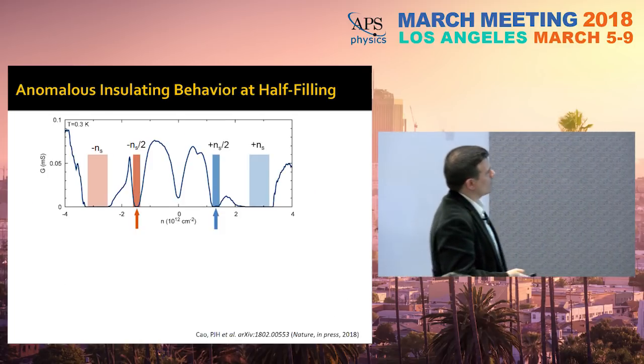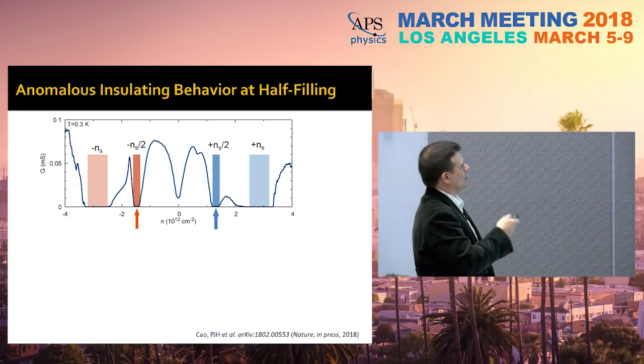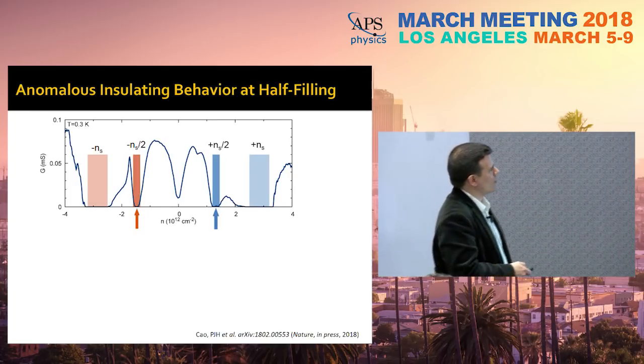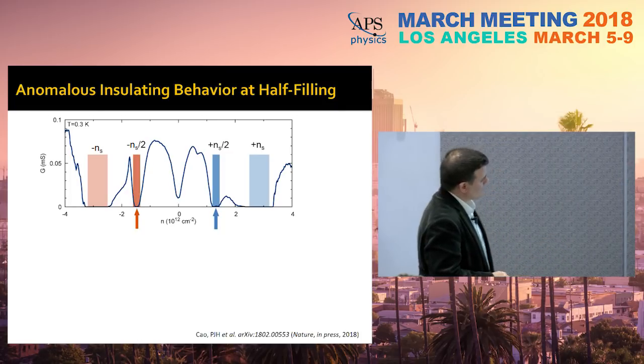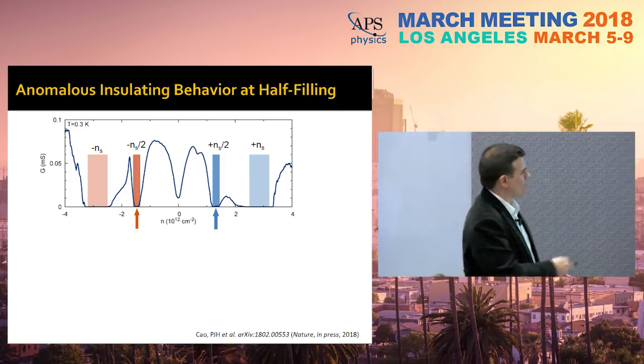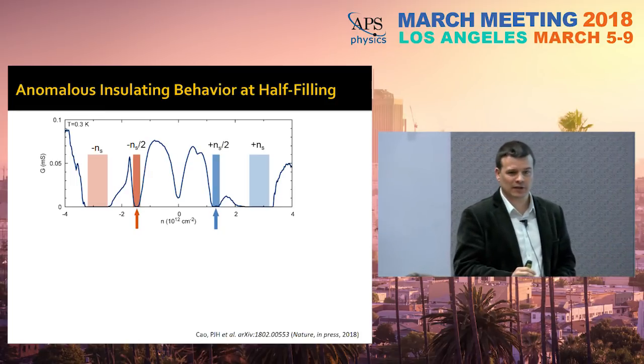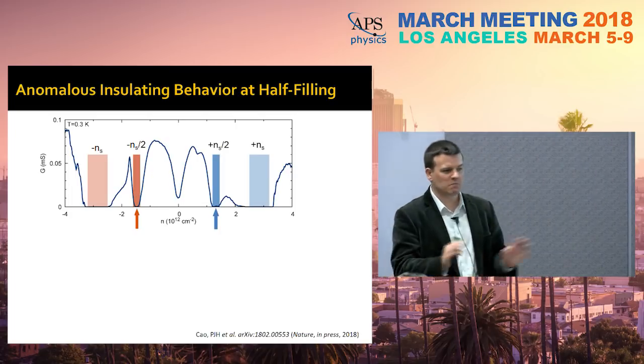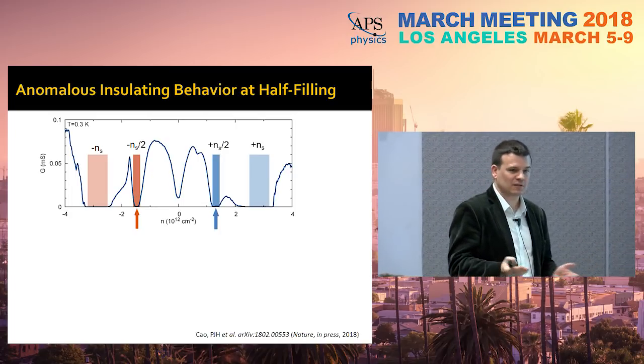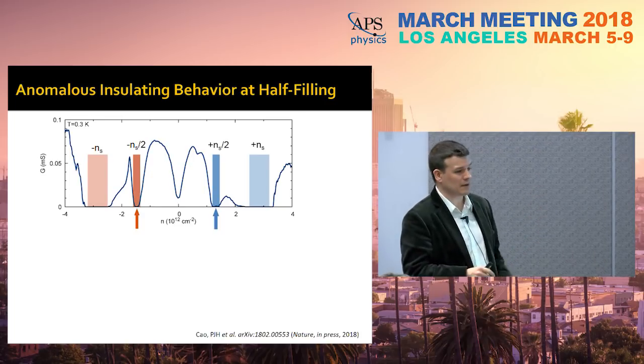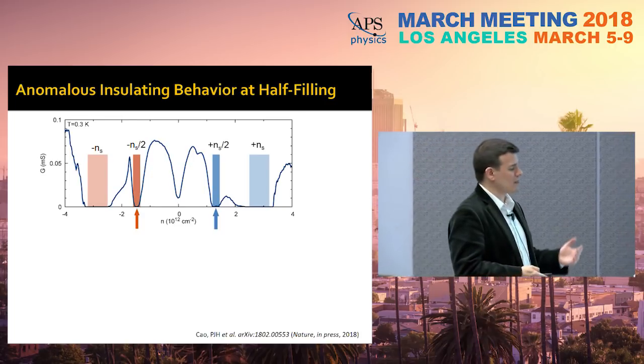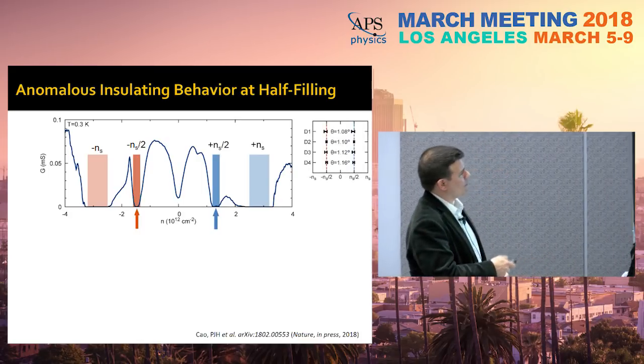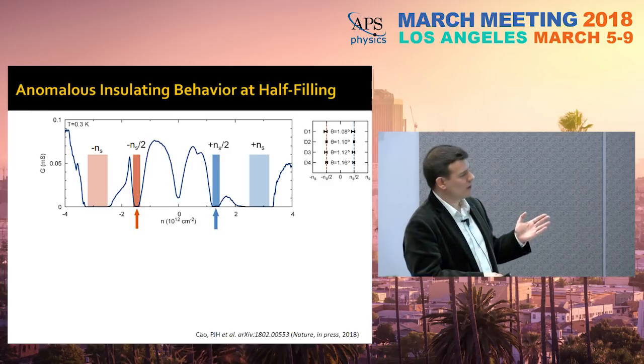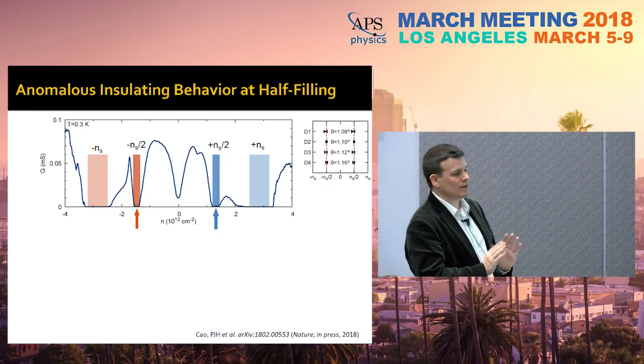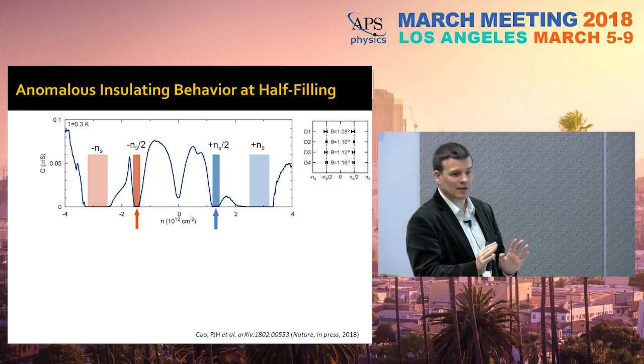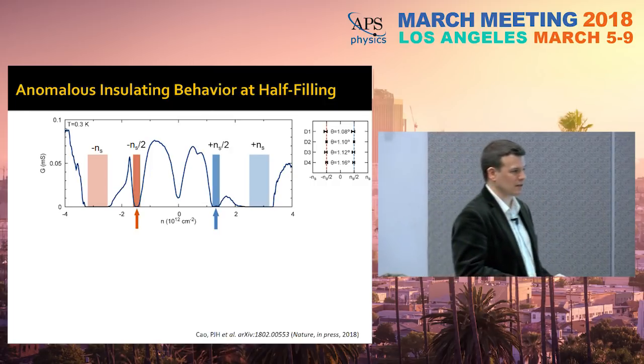So when we did this, and you can see now the actual conductivity with real units and density, okay? We saw these two insulating states. And we realized immediately that these were very different from these other two insulating states or any other insulating states we had seen in graphene, bilayer graphene, graphene on hBN. There are many, many systems in which you can gap out graphene doing various tricks. In all of those systems, this insulating behavior was very, very different. By the way, this only occurs for angles within around 0.1 degrees of the magic angle. If you're 0.2 degrees away from the magic angle, all of this disappears. Okay? We never see this insulating state at half filling.